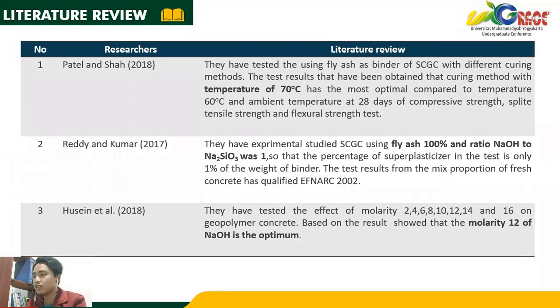So this is the literature review. We use the literature review by Patel and Shah 2018. They tested using fly ash as the binder of SCGC with different curing methods. The test results obtained show that the curing method with a temperature of 70 degrees Celsius was the most optimal compared to the temperature of 60 degrees Celsius and ambient temperature at 28 days.